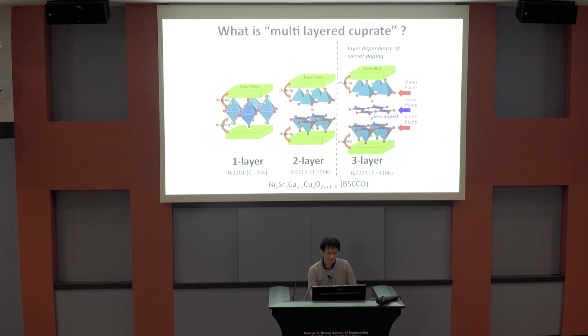But in the multi-layer system, with 3 or more layers per unit cell, you can distinguish different coupled layers. One is just adjacent to the block layer, so carrier is more doped. Another one is protected, or far from this dopant layer, so carrier doping level is less than the outer layer. Protected means there is no disorder, so you can expect it to be very clean.